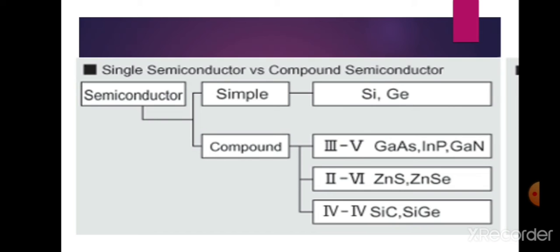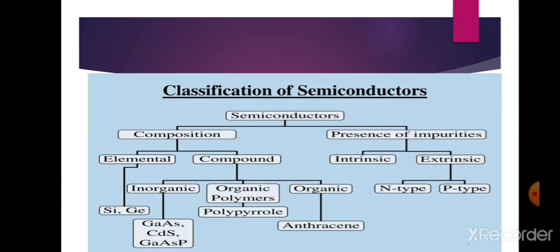This is evidenced by the fact that each of these compounds has a higher melting point and a larger band gap compared to 4th group elements. For example, we consider indium antimonide and alpha tin. These substances have the same lattice constant and the same average atomic number and atomic weight. On the basis of purely covalent bonding, the two should exhibit the same properties. However, because of partial ionic character of bonds in indium antimonide, it has a higher melting point, that is of the order of 525 degrees centigrade, and larger band gap of the order of 0.17 electron volt at 300 Kelvin.